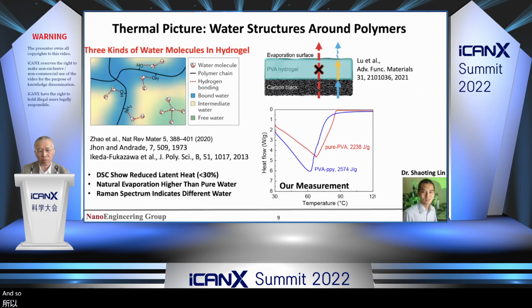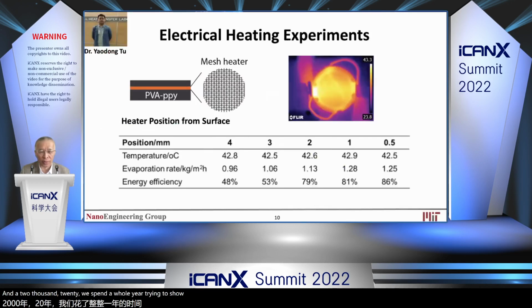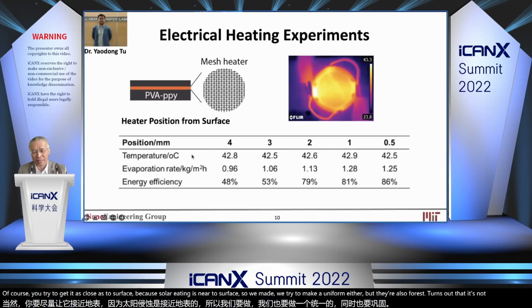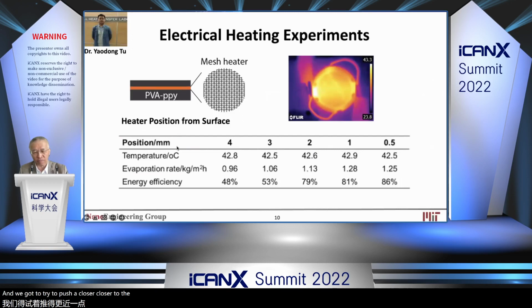But on the other hand, we said, okay, maybe it is a thermal effect. And this was actually around the end of 2019. And in 2020, we spent the whole year trying to show whether a thermal effect can explain it. If it's thermal, you can heat up a different way. You can use electrical heating. Of course, you try to get it as close to the surface as possible, because solar heating is near the surface. So we tried to make a uniform heater, but also porous. It turns out that it's not easy. And we tried to push closer to the surface, and you can see different distances from the surface. On the other hand, you can see the evaporation rate never gets above the thermal limit, 1.4, 1.5. We don't get that, right?